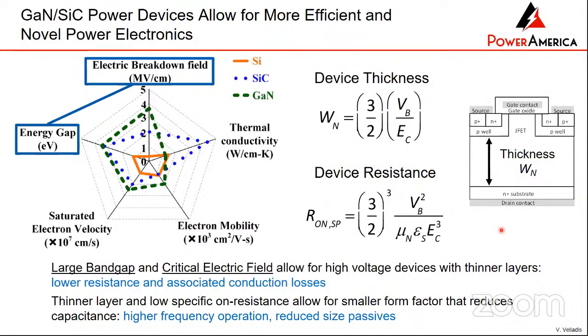So what are the properties that make silicon carbide and GaN desirable for power electronics? Number one, the large band gap allows devices to be made with low resistance. And obviously, if you have low resistance, you have lower conduction losses, right? And because of the large band gap and critical electric field, you can make thinner layers. And when the layer is thin, then you can operate at higher frequency. And that's very, very important.